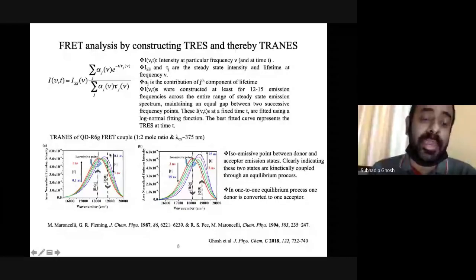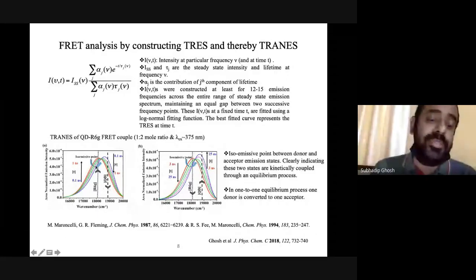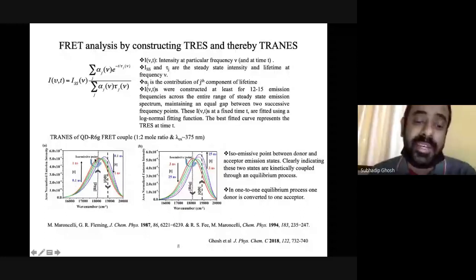Now we found that as time progresses, the emission intensity of the quantum dot portion decreases, but at the same time the emission intensity of the rhodamine 6G portion increases. And again we found, like in the steady state, in the time-resolved study also there is an isoemissive point, and this is indicating FRET is going on.